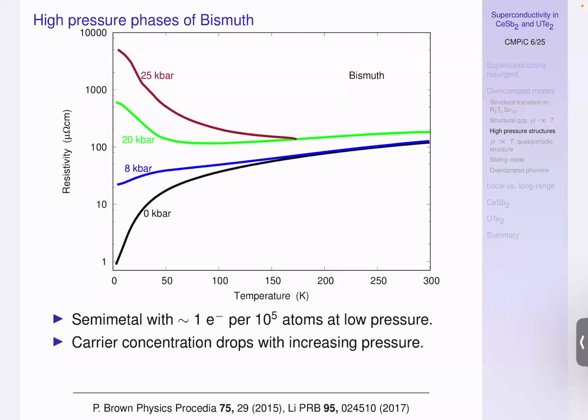So you can use this logarithmic scale. You go from 1 microohm-centimeter here to 8,000 or 9,000 microohm-centimeters. So many orders of magnitude increase in the low temperature resistivity. But that's known, and it's kind of interesting, but we actually then focus on something else.